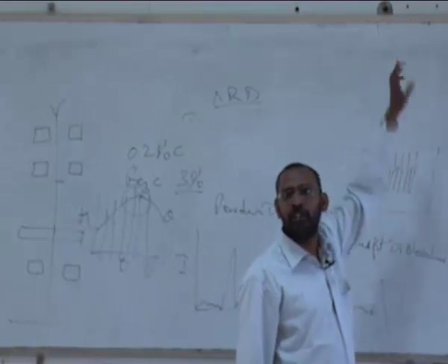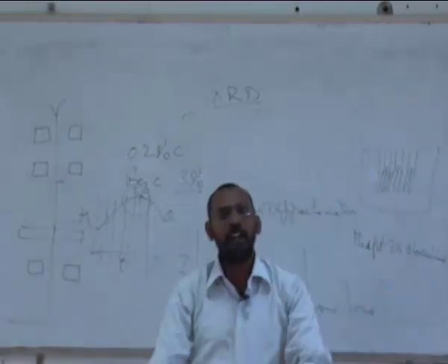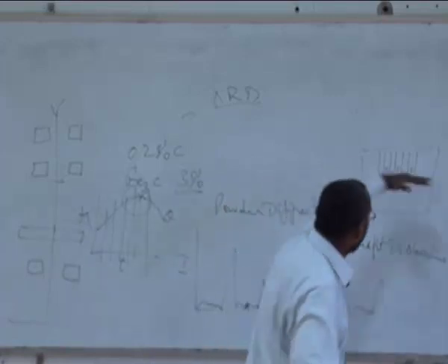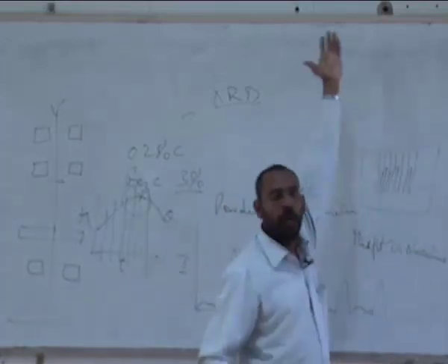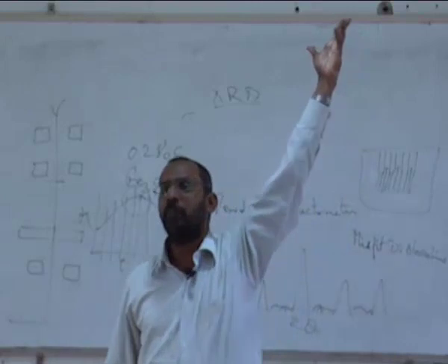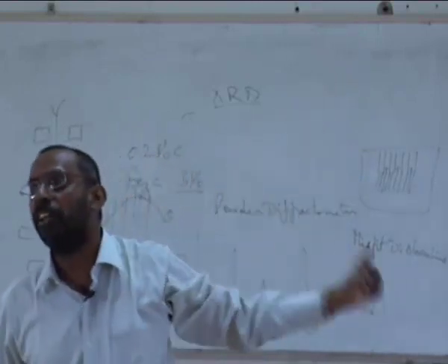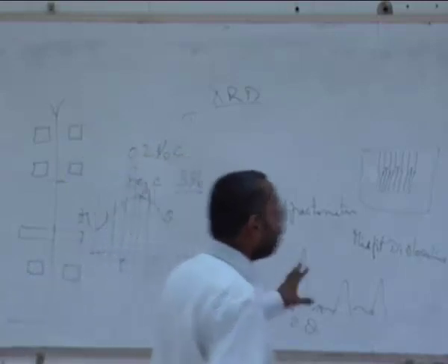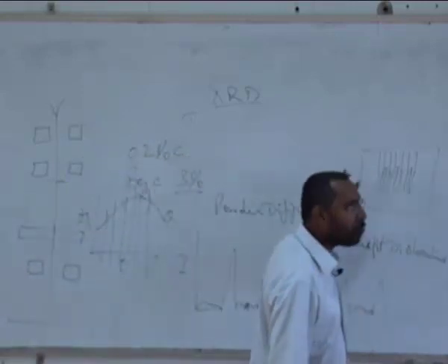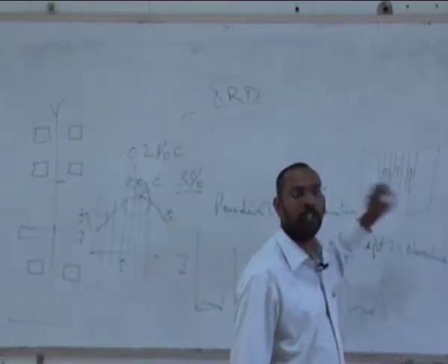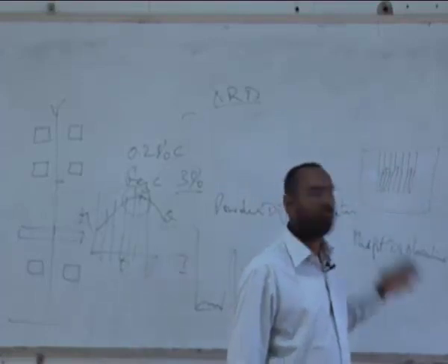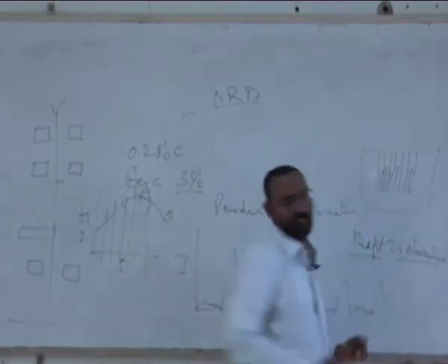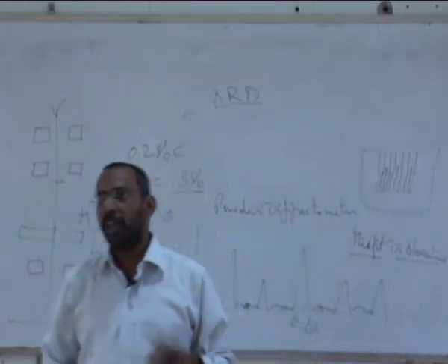because there is a plane in the precipitate, but there is no continuous plane in the matrix on the other side. So that means there is an extra plane of atoms below this interface plane, and there is no corresponding set of atoms above this plane. So that is what we call an edge dislocation, right? These dislocations come because of a mismatch between the matrix and the precipitate, and that's why we call them misfit dislocations, because there is a misfit.